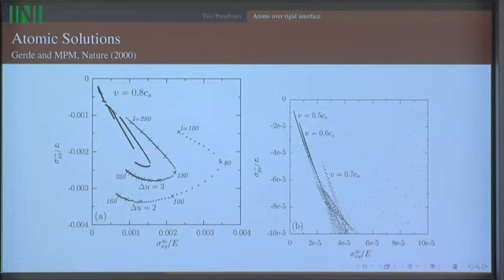And what I have with all these little dots is I have cataloged cases where we claim that little bubbles can exist and can run as self-healing cracks along the interface. The numbers indicate the lengths of the bubbles, and these things delta U indicate the amount that the bubbles close in or close up.